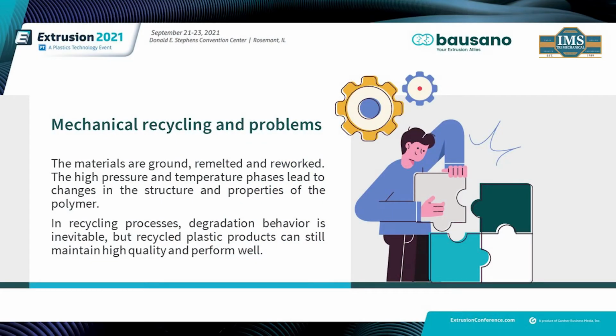In fact, reprocessing recycled polyolefins is always accompanied with degradation, crystallization, and consequently there are processability issues. This is a result of the molecular chain scission, branching, and cross-linking. The degradation behavior decreases tensile strength and impact strength. In recycling processes, the behavior is inevitable, but the recycled product can still maintain quality and perform adequately.